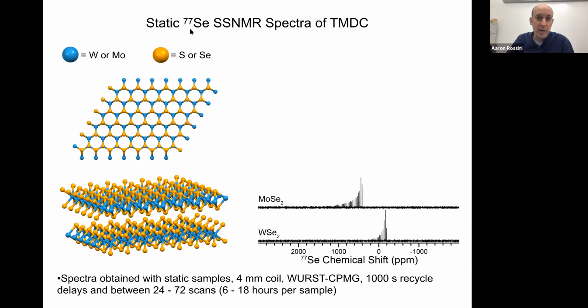So we started by doing some selenium-77 solid-state NMR to see if we could follow the transformations of these compounds when you do the ball milling and annealing. So the structure of these materials is shown here. In these materials, each of the metal atoms, which is going to be tungsten or molybdenum, is coordinated by 6 selenium or sulfur atoms. And then each of the seleniums or sulfurs has a trigonal pyramidal geometry where you're going to have bonds to 3 metal atoms.